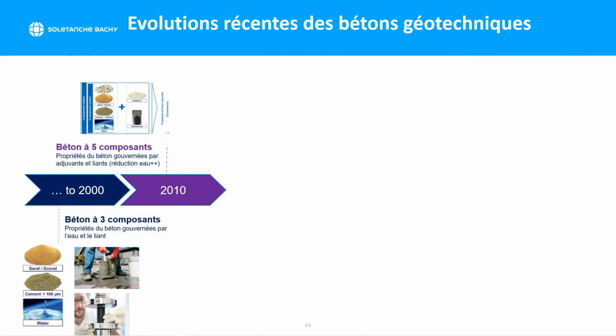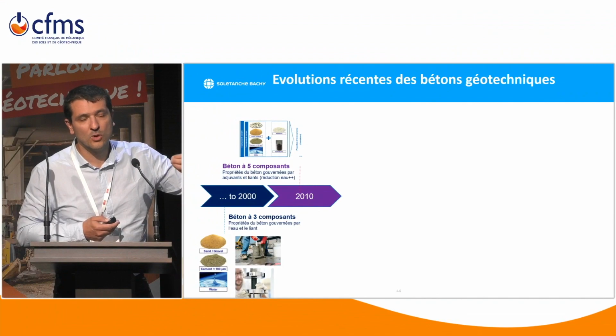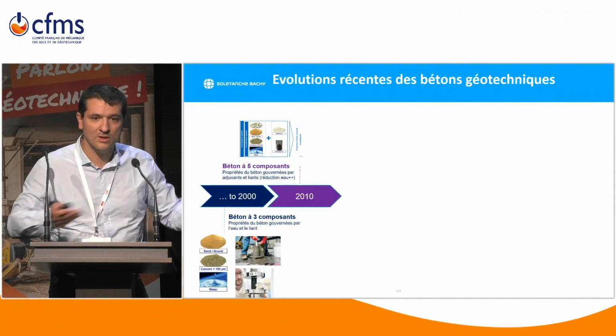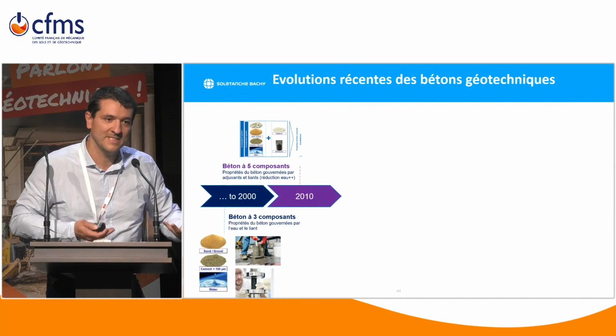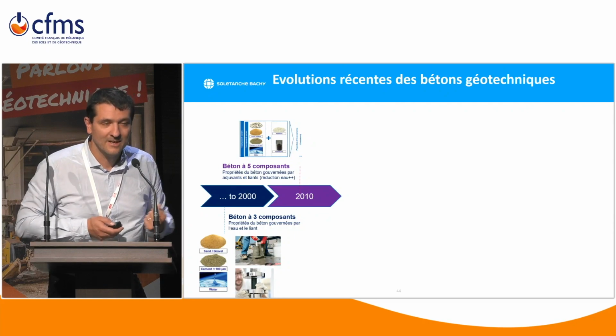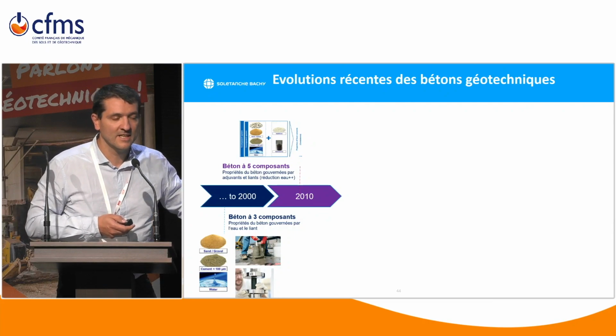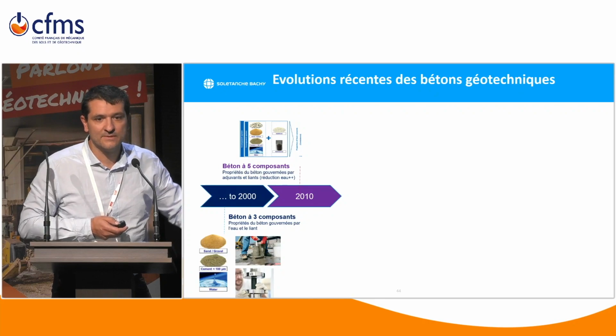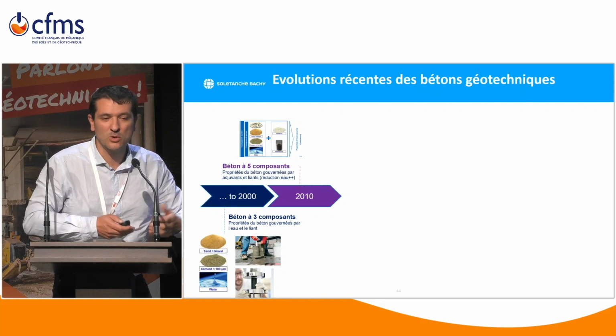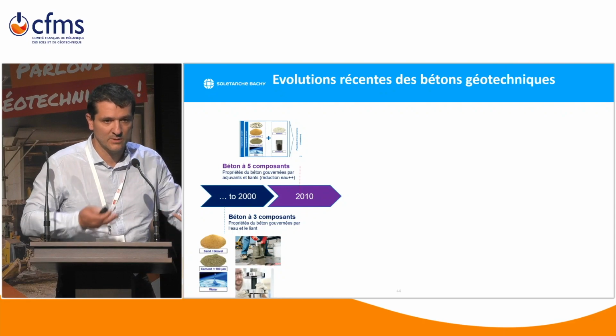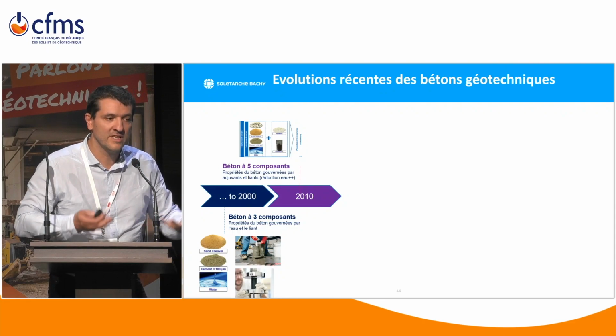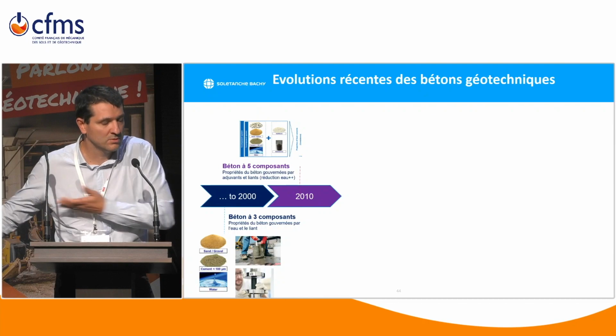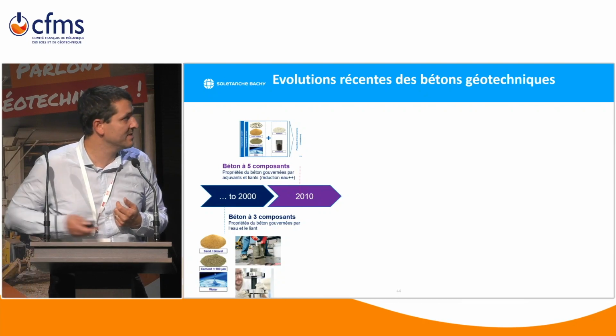And the admixtures help to reduce the water and get higher strength. But at the same time, by reducing the water, they give you a concrete that is more sensitive to variation. And as the concrete is more sensitive, especially for geotechnical concrete, it was not enough to just test what we call the slump and the strength, because it was not enough to fully characterize the concrete that we need to pour at 70 meter depth.